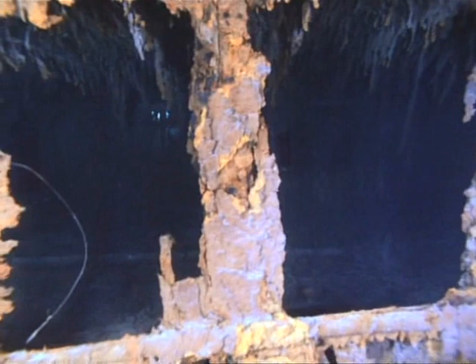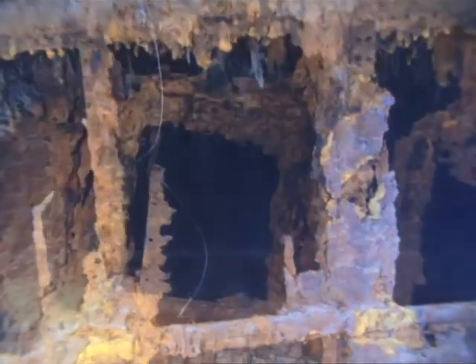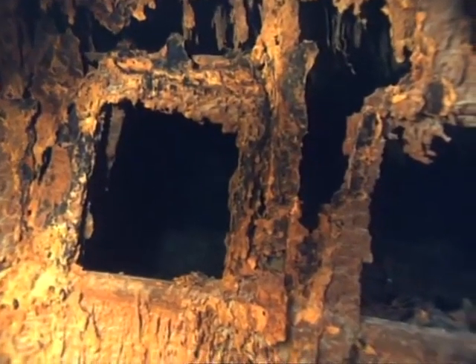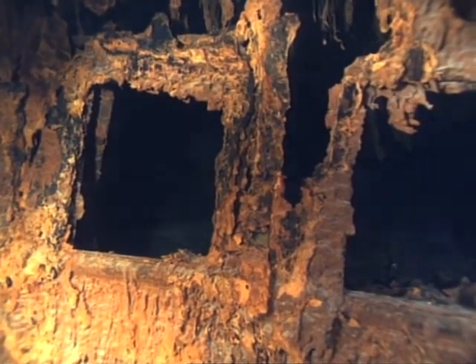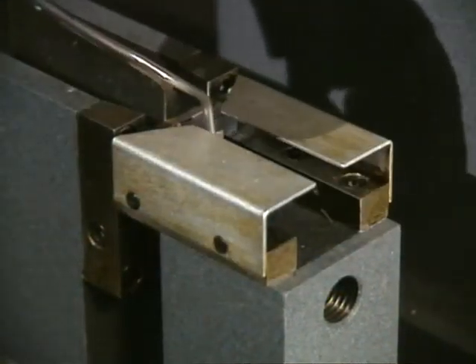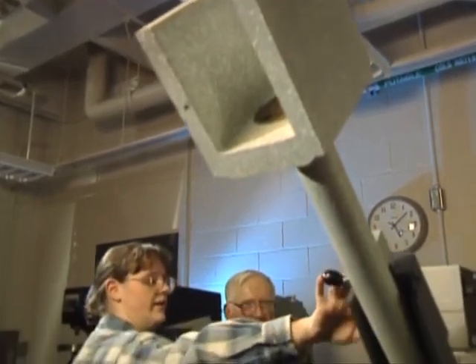At the time the Titanic was built, no one suspected that these chemical impurities could make steel fragile under extreme conditions. Investigators suspect that the extreme cold water temperatures of the North Atlantic caused the steel to become even more brittle. The waters of April 14 to 15, 1912 were unusually cold for the Atlantic at that time of year. 28 degree seawater is not the ordinary seawater you find in April. H.P. Lely chills a bar of Titanic steel to the water temperature the night of the disaster. The sample will be subjected to a violent impact.